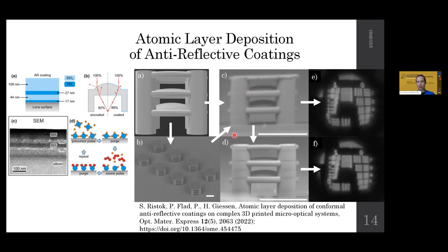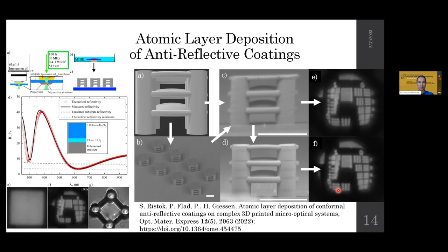We see before and after coating. The image is brighter and clearer in the bottom one because we could coat it with a conductive layer needed for SEM. But in both cases, we see that imaging is possible, and the imaging with the anti-reflective coating is increased. The contrast becomes better, which is as expected.